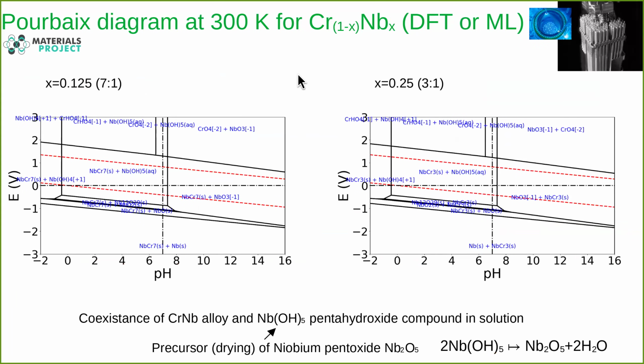So here you can see an example that we took with our collaborators, to know how chromium niobium will perform at 300 degrees. It's 300 degrees C. No, it's 300 Kelvin. Sorry, yes. And then a different concentration. So you see the different concentrations, the calculated Pourbaix diagram is shown here. With that concentration, if you take normal water pH, which is also kept in nuclear reactors close to neutral, so around 7, you will see that the stable phase will be here.